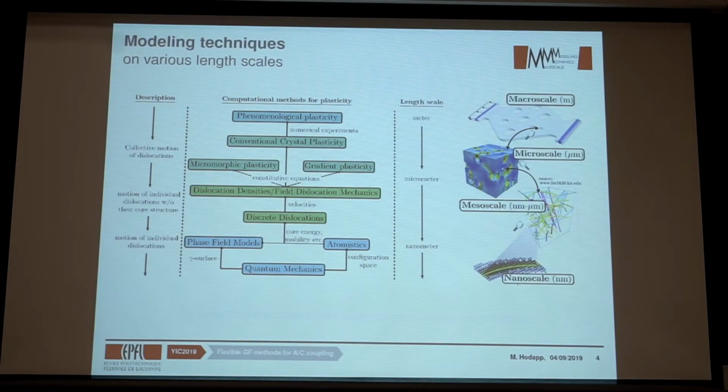And with these quantities, you can fit your atomistic potential. With an atomistic potential, you can do a bit more. You can characterize your deformation on the dislocation level. You can compute long dislocations. You can compute dislocation loops. Essentially, you can compute energy barriers and core energies of these dislocations with which you can feed higher scale models, for example, discrete dislocation dynamics.